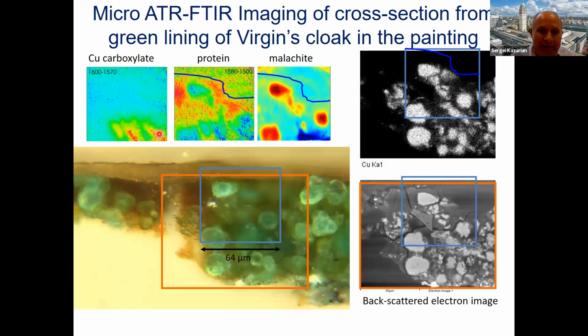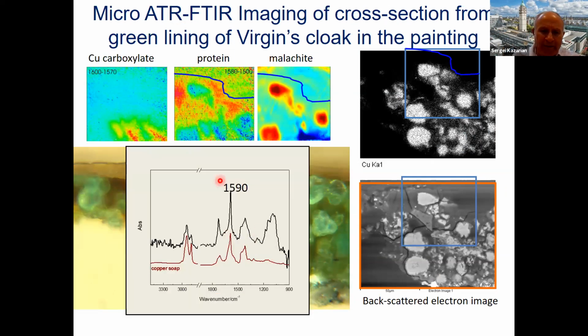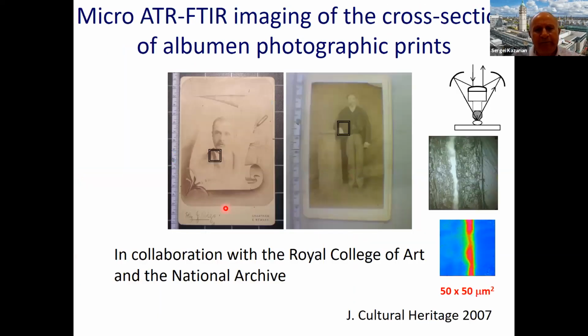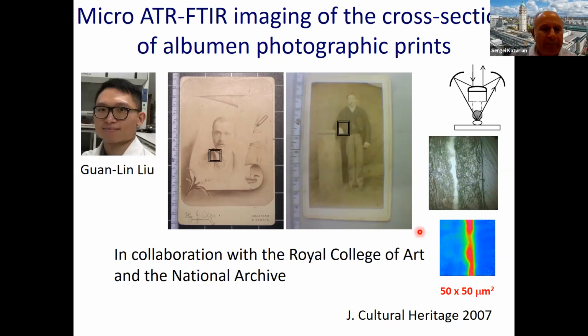And importantly, we were able to detect something else apart from malachite and protein, and it was copper carboxylate. So again, this is a type of material, carboxylates called metal soaps, that sometimes disrupt paintings. And we detected it unambiguously by the presence of this spectral band. It's just one slide on another example, because we collaborated with the Royal College of Art at the same time, some years ago now, when we studied albumen photographic prints. And this layer here is a very thin layer, about a few micrometer. It was showing, again, a product of albumen, and that's what's important. And I unfortunately don't have time for details of this study. But my current student, Guan Lin, is now studying other albumen photographs of the end of the 19th, beginning of the 20th century, and their degradation.